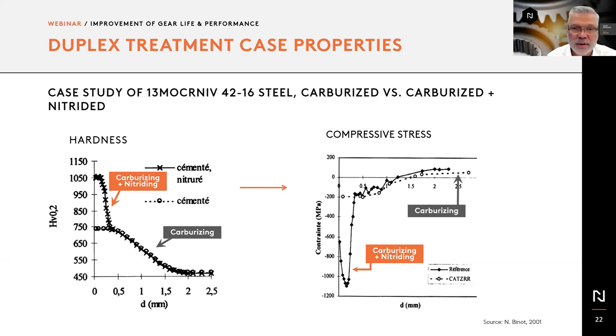So of course, the nitriding process in this case will yield a much harder surface, but also produce a compressive stress on the surface, which will help the part withstand higher bending, fatigue, etc. But the important part is that nitriding processes can be formulated for very low temperatures, so from below even 750 degrees Fahrenheit or 400 degrees Celsius. So we can avoid tempering again the carburized component. So the processes have to be adjusted, obviously, but this type of duplex process can be and is performed.